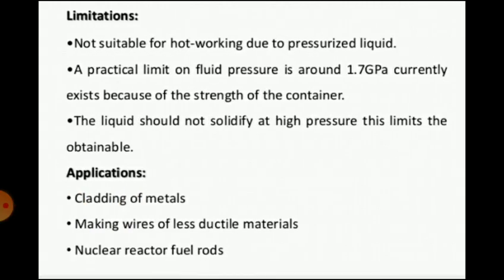Limitations: not suitable for hot working due to the pressurized liquid. A practical limit on fluid pressure of around 1.7 GPa currently exists because of the strength of the container. Applications: cladding of metals, making wires of less ductile materials, and nuclear reactor fuel rods.